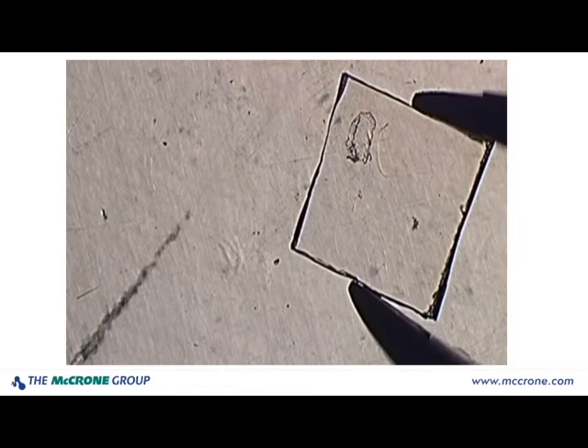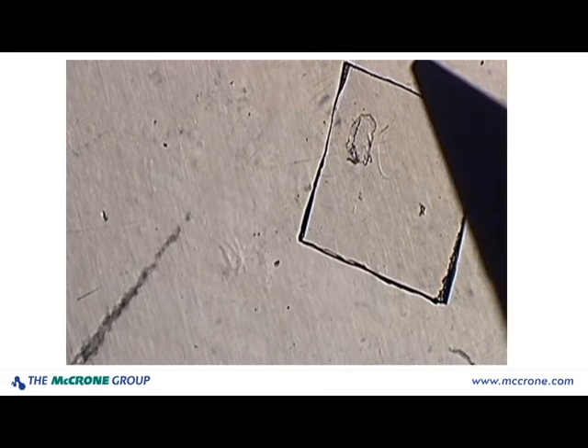It has to now be pressed out again, so I'm going to cover it with the micro cover glass, apply pressure with my carbide scribe, and drag it off as I did in the previous video. Some polymers tend to stick a little bit to the micro cover glass, so that step may have to be repeated a few times.